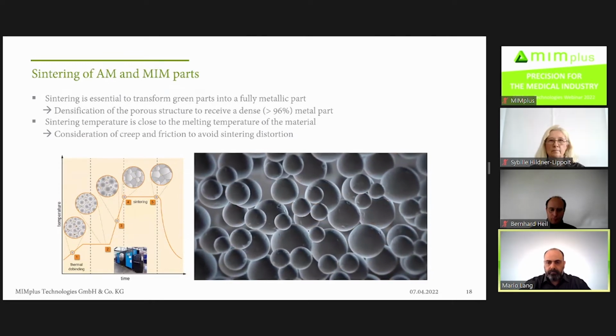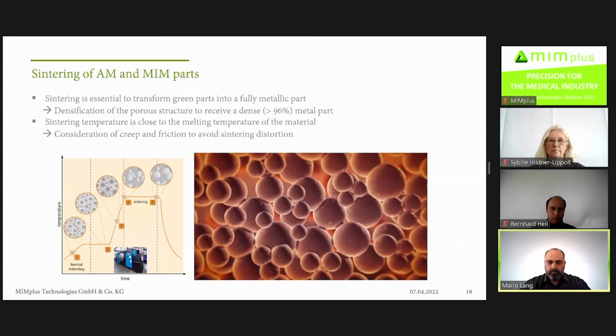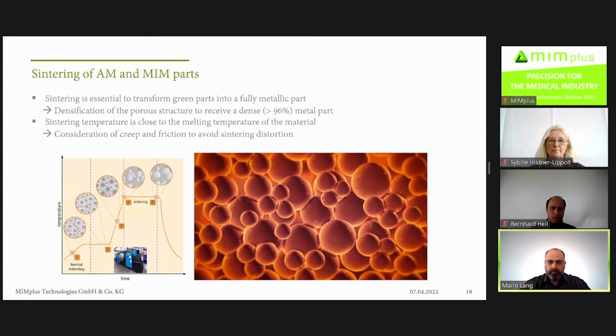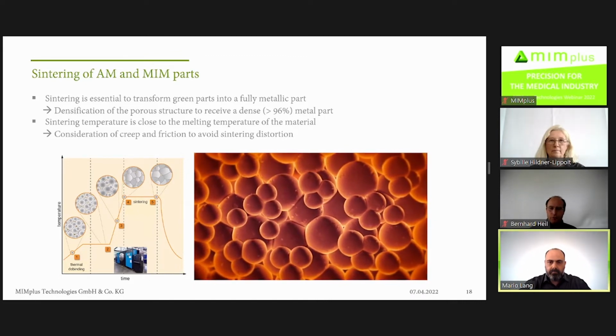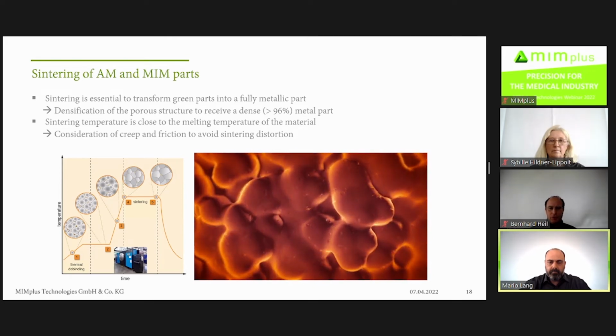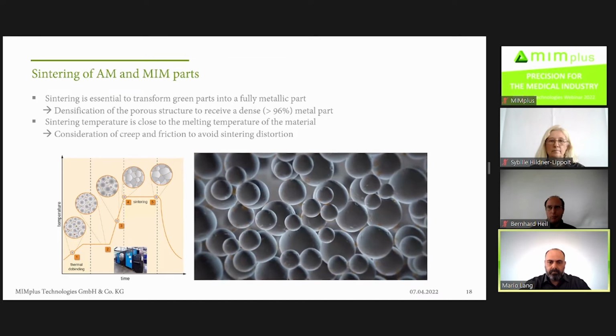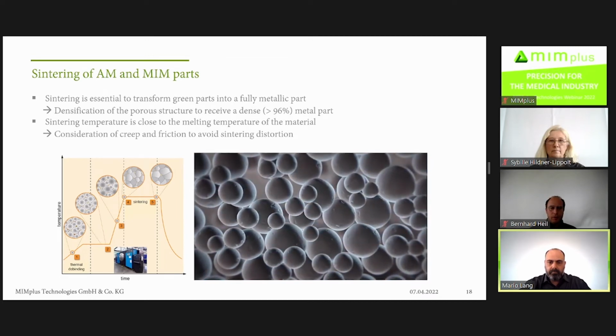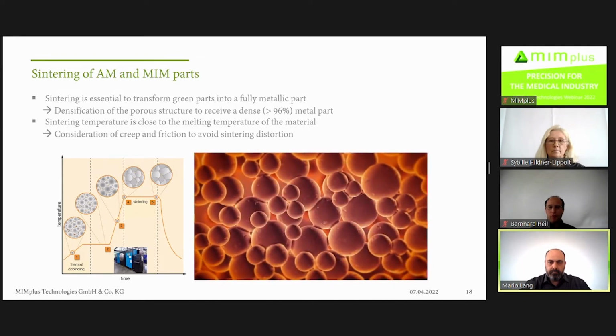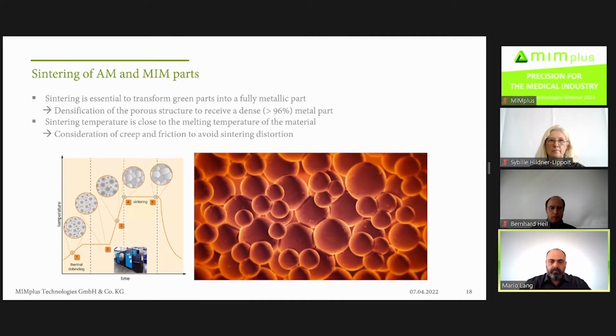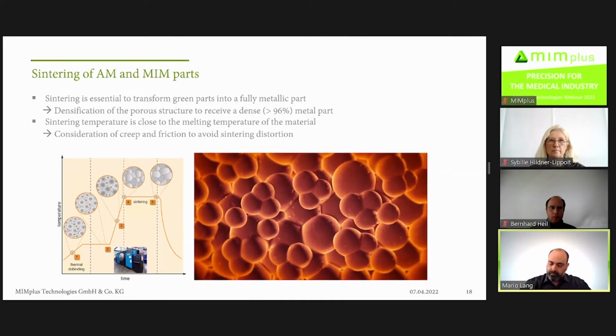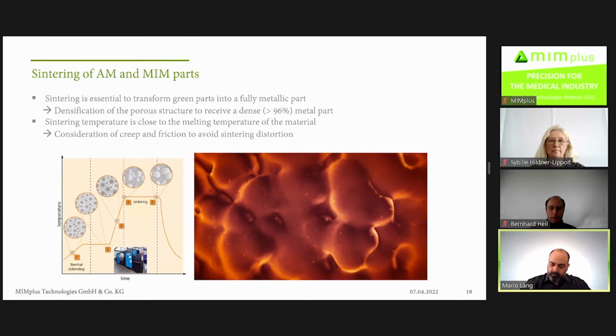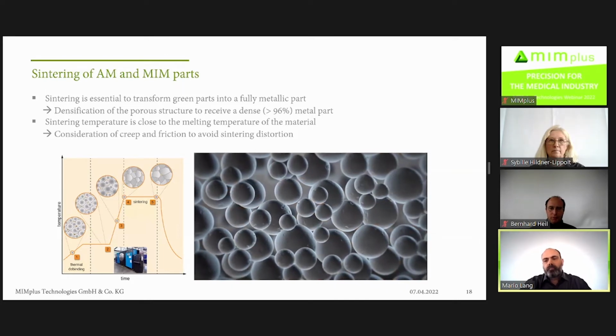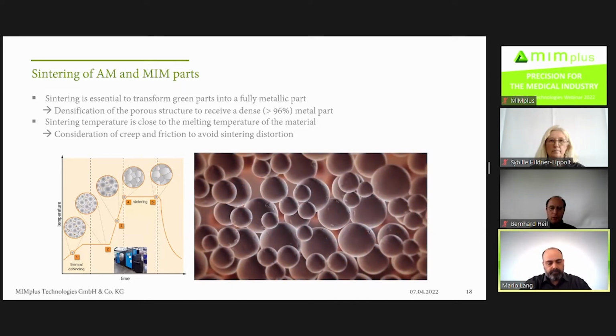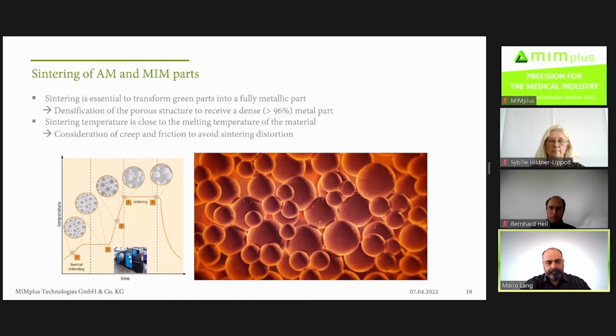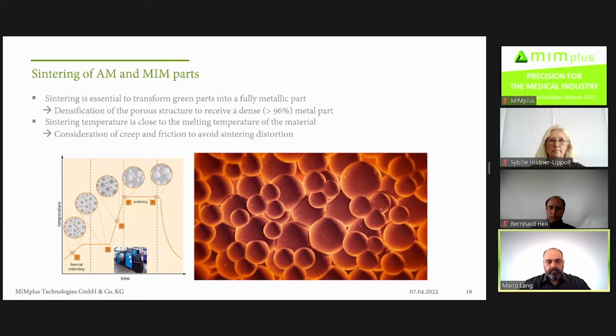After having shaped your feedstock or have your green parts and debind it, you have the sintering process, which is heating up the part and removing the rest binder and then heating up to sinter temperature, which is around about 1300 degrees Celsius. And then you sinter the parts together, you remove the porosity of the parts and you get the dense sinter parts. Of course, in this process step, you have only low strength of your part, and you have the shrinkage, and you have the friction between your sinter plate and so on, and you have to think of how can the part deform in this process and what can you do to avoid this. That's something you have to think of in the design.